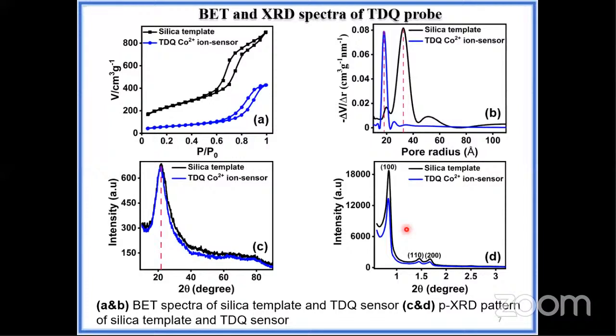After that, we fabricated the probe onto the silica monolithic material by the direct immobilization method. We also investigated the properties of the material before and after fabrication. In BET, it shows a decrease in the surface area and also a decrease in the pore volume. So it indicates that the probe molecule is highly arranged in the silica monolithic material. Also in wide angle XRD, both materials, before and after fabrication, show an amorphous nature, and it confirms there is no damage in the material. It's showing the original position.